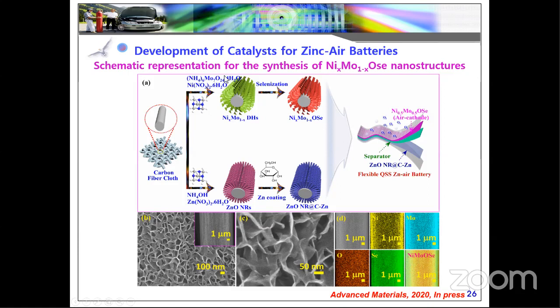That air cathode material and the newly developed zinc nanorods, 3D nanostructures and air cathodes, we finally fabricate with quasi-solid-state electrolytes, especially PVA with KOH media, and we fabricate the device, especially flexible energy storage zinc-air batteries. Before fabricating, we need to evaluate them one by one, starting with morphological analysis. In the morphological analysis, first we want to prove we are growing directly on the carbon cloth.